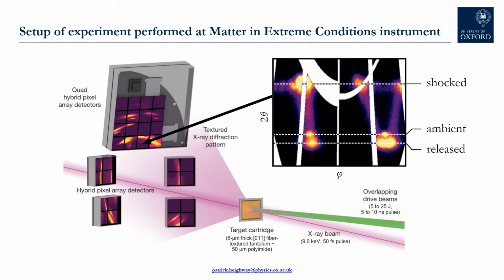We see first that there are strong diffraction peaks at high values of scattering angle 2 theta, which comes from that fraction of the foil that is yet to release. We then see a continuous streak of diffraction intensity moving back towards lower Bragg angles. This of course comes from the gamut of density states present in the release fan. And finally, we also find strong diffraction peaks at relatively low scattering angles that comes from the fully released material.